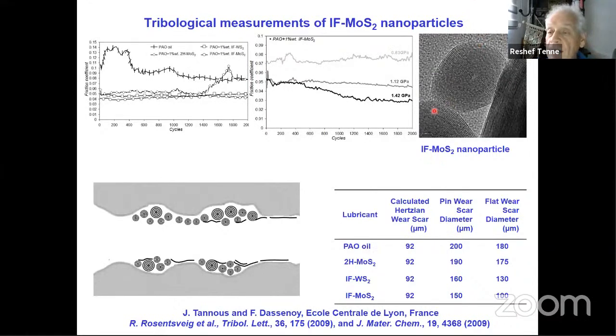And here is a very small example out of many, many studies, which shows you these Fullerene-like nanoparticles getting in between the surfaces of metal and lubricating together with oil. They are added at 1% or less into the oil, and they lubricate the surfaces very well under high loads. This graph shows the friction of oil by itself as a function of time, and you see that after some time, the friction goes to 0.1. But when you use these Fullerene-like nanoparticles, the friction is cut by half. And if you use platelets of molybdenum disulfide, it is also very small initially, but eventually the friction goes up because the molybdenum disulfide platelets are burned.